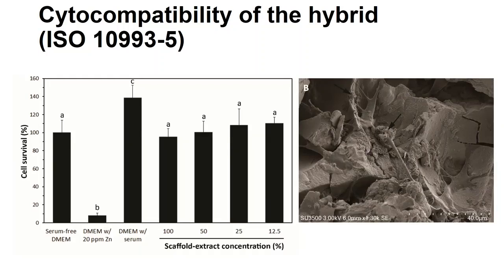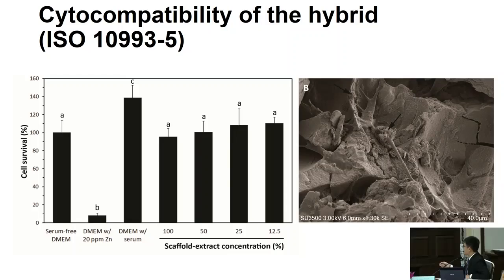And we next tried to prove that our hybrid scaffold has biosafety. So we did a cytocompatibility test in accordance with the ISO standard. When we extracted the degradation product of the hybrid scaffold, we used the extract to culture the fibroblast cells, and we found that the survival of the cells in the media containing the degradation product of the hybrid is very close to the control. This means that our hybrid is safe.